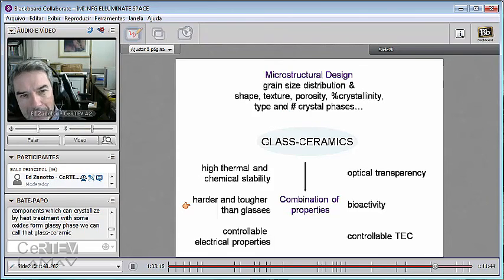And you can have high thermal and chemical stability. And here, starting to answer that question, the toughness of most glass ceramics that I know varies from 1 to about 5 megapascal square root of meter. And the toughness of glasses is 0.5 to 0.7. So glass ceramics are in general much tougher, usually 5 to 10 times tougher than glasses, which is good. If you recall, this is one of the most negative properties of glass, their fragility, low toughness.